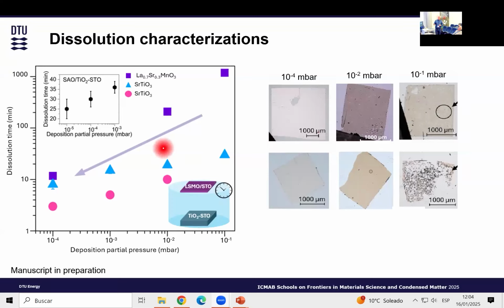Anyway, what I want to say here is that the dissolution time depends on the partial pressure. And at the pressure of 10 to the minus 4 for the growth, we got some good conditions for the membrane. When I say good conditions, you may ask what I mean. For example, for the LSMO, we also did some characterization. We looked at the magnetization before and after, and we can see that the properties are the same. So we had to characterize them beyond just looking at the substrate and determining by its size or by the fact that you cannot see, and I cannot see from here, whether there is a crack, and there are a lot of cracks in some of them. So one of the characterization techniques for us was to physically characterize the material